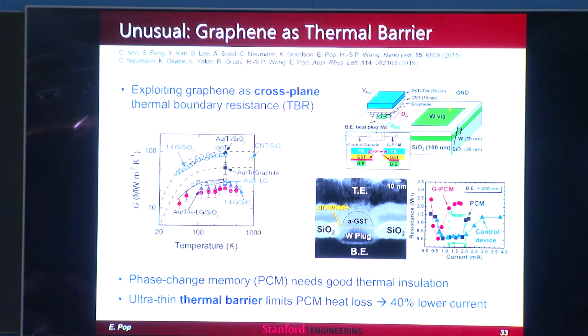But it turns out in electronics there's an application. An immediate application is in phase change memory. In phase change memory, you really need a decent electrical conductor, but a lousy thermal conductor, to thermally insulate a little memory cell or a memory bit, right? And what's unusual here is that at first we just used graphene as a thermal barrier. And again, people say, well, graphene's got a good thermal conductivity. What are you doing? But it turns out that out of plane, graphene by itself really blocks heat flow. And we got 40% programming current reduction for this type of memory technology.